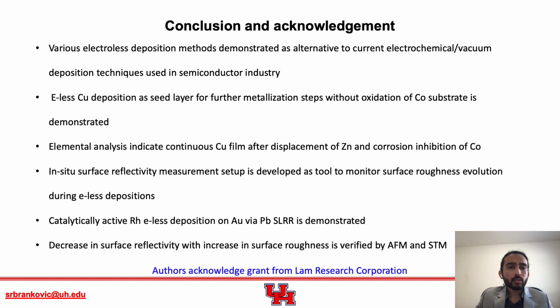We have developed in situ surface reflectivity measurement setup at University of Houston, which serves as a tool to monitor surface roughness evolution during various electroless deposition process, whether being homoepitaxial deposition or heteroepitaxial deposition. And we have proved this with electroless rhodium deposition on gold, as well as electroless copper deposition on copper. And in terms of rhodium deposition, we have demonstrated that we can deposit catalytically active rhodium with a few cycles of the electroless deposition as well. Overall, the decrease in surface reflectivity with increase in surface roughness for all the experiments is verified by AFM and STM.